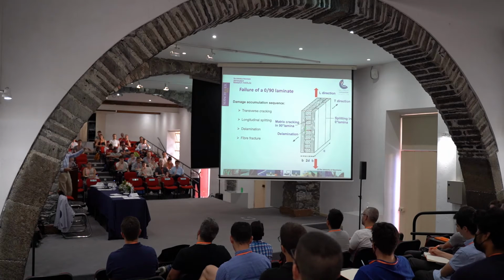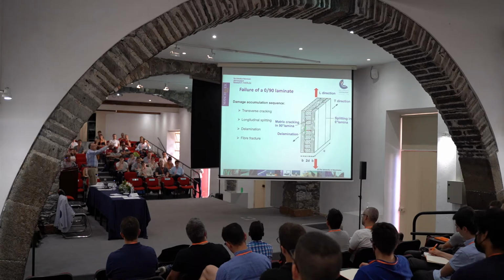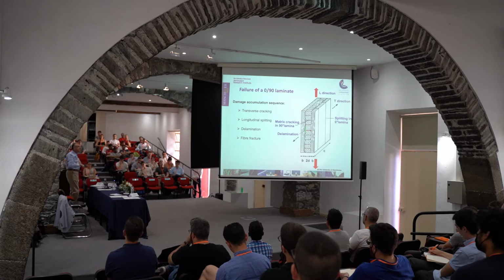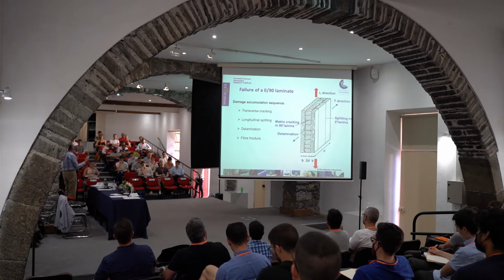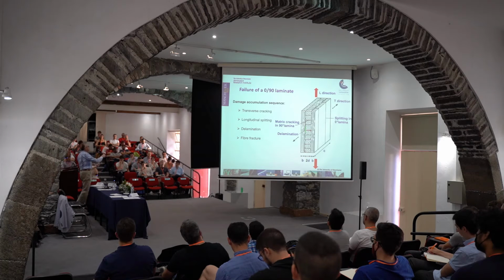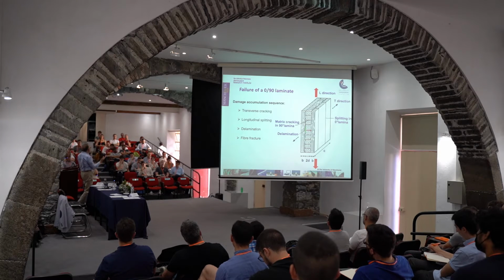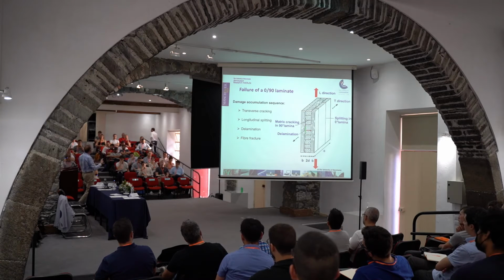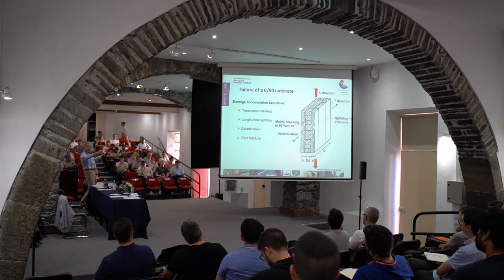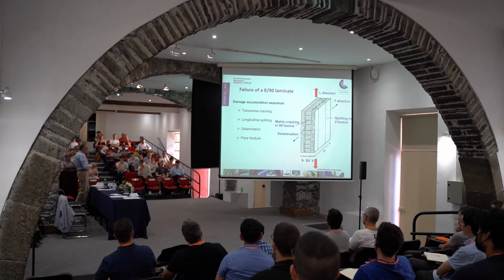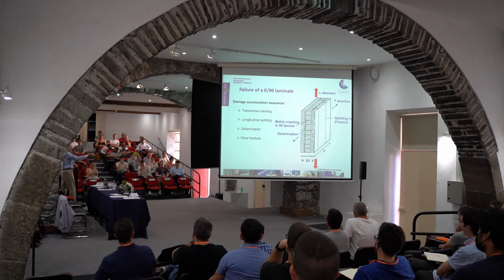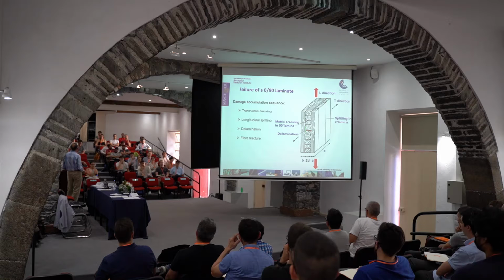So it's going to affect all the elastic properties: the Young's modulus in the axial direction, the transverse direction, the shear direction, and so on and so forth. Plus, of course, that kind of damage is going to allow the environment to get into my composite structure, so it can be quite damaging. And then structures are not just under uniaxial tension; they are under biaxial or multi-axial in-plane and out-of-plane loading that introduces additional stresses. So if I apply tension now in the transverse direction, the zero layer is going to split. I'm going to get axial splits, and at the tip of the split I'm going to get more delaminations.